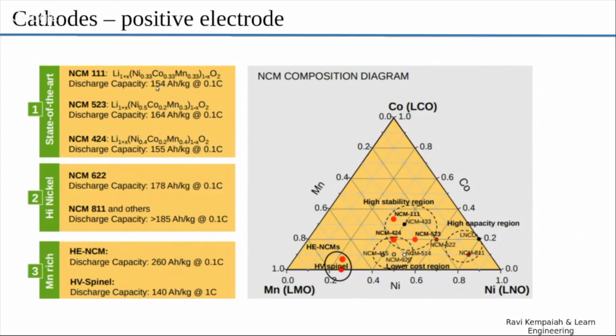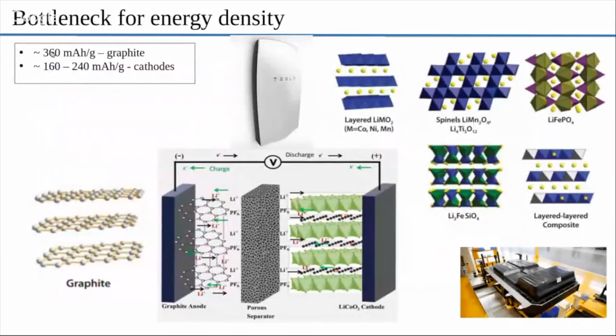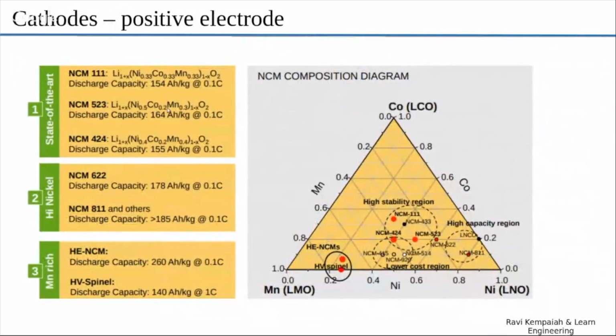And they had capacities of around 150 to 160. As you see, this is less than the anode, which is 360. Sorry, the anode already has 360, and the cathode is the weaker point. So they had 154, 164, 155 milliamp hour per gram. Now people have optimized the chemistry to go with less cobalt and increase the energy density.